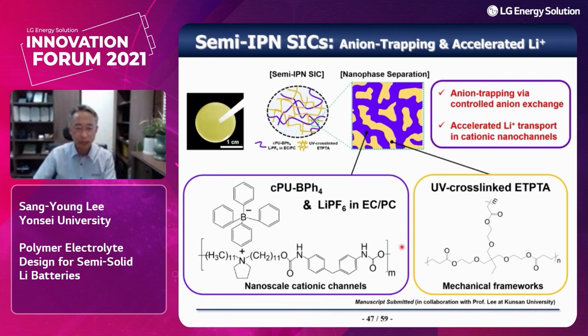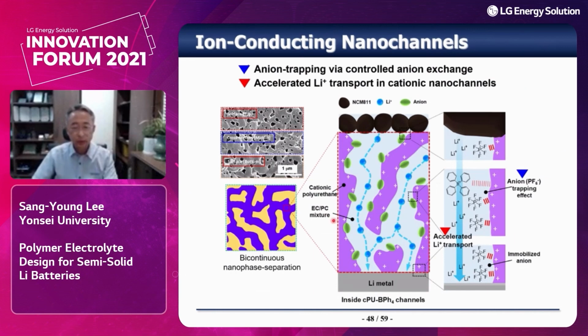And then in terms of electrochemical performance, our attention was paid to the purple region. Through the purple region, we expect an anion trapping effect via controlled anion exchange reaction. And also another interesting finding is accelerated lithium-ion transport through the cationic nanochannels. Okay, so here I have already mentioned the anion trapping effect via the controlled anion exchange near the cationic polymer walls like this. And another interesting finding is we have designed the cationic nanoscale channels. Through the nanoscale channels, we expect the lithium-ion transport can be accelerated. Okay, so this is the evidence.